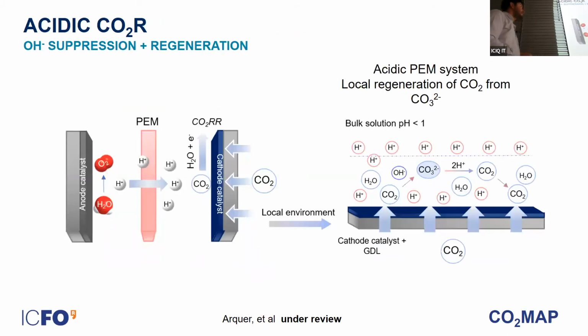A second strategy that's also interesting is to move away from alkaline completely. So what if you could perform the CO2 reduction reaction in an acidic electrolyzer in such a way that all the CO2 that you enter in the system could be transformed directly into the product of interest, and any probable molecule of CO2 that was converted into carbonate based on the local generation of hydroxyl groups that happens normally when you have a reducing cathode would be converted back to CO2 by the presence of a lot of protons around, because your electrolyte is very, very acidic.